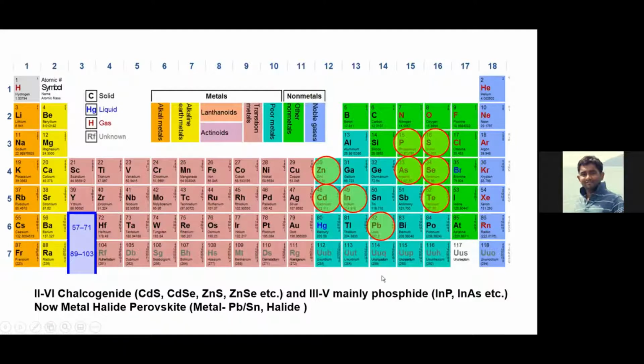Also IV-VI materials. People don't use tin, because tin has different oxidation numbers, like +2 and +4, and it oxidizes very fast in the air. So people only use lead: lead sulfide, lead selenide, lead telluride. Though they are toxic, these are very good materials for thermal imaging and other things, because they emit in the NIR. And nowadays most people work on metal halide perovskites, or organic-inorganic halide perovskites. Generally people choose the metal as lead, tin, and nowadays indium, as double perovskites and other things. For halides, they generally choose iodine and bromine, and fewer chlorine, because chlorine is very small in size. That's why nowadays it's not very good for different applications, and chlorine is not famous for perovskite nanocrystals.